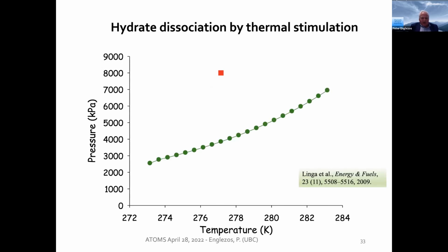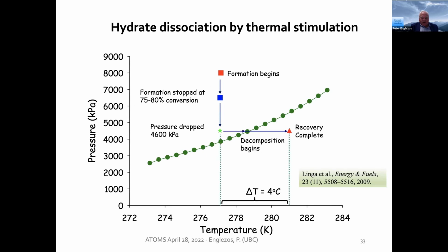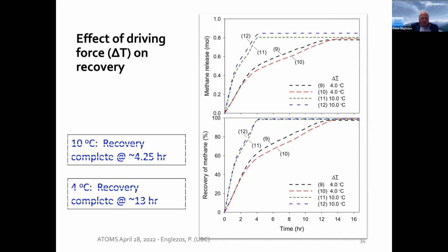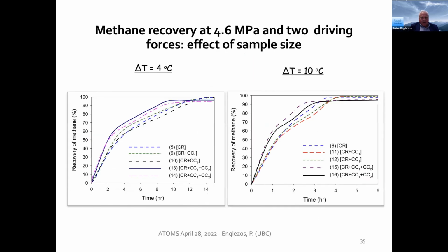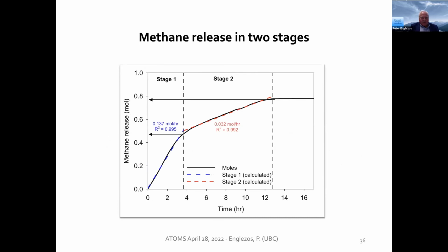And therefore, the postulated sequence of induction time, nucleation, growth for modeling is not necessarily valid when you're looking at hydrate formation in porous media. We looked then at hydrate dissociation, and at thermally stimulating a hydrate by moving into the unstable regime. The delta T is the driving force. And then we started grouping the data in terms of the driving force, 10 and 4 degrees C. By looking at data with the same driving force but different bed size, we could see that in all cases we see a two-step process, which can be correlated quite well.